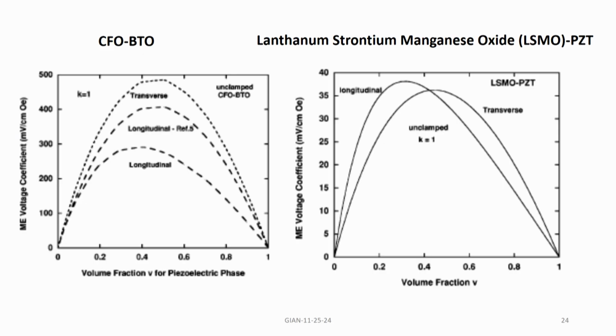But I want to make sure that you understand the key difference between this oxide, which is ferromagnetic, versus the spinel ferrites, which are ferrimagnetic, or hexagonal ferrite, because it has super exchange, this is double exchange. Okay. It's ferromagnetic, but the Curie temperature is very small, close to room temperature, and this is not the material you want to use in a composite, because it will lose its coupling just slightly above room temperature, and you don't want to use it if you can.